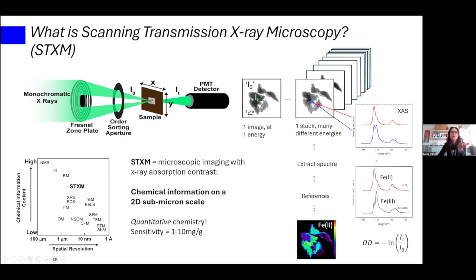So I've shown it to you here for the iron edge, but you can do other edges as well. We do cover the carbon edge, the nitrogen edge, the oxygen edge, the calcium edge, you name it, we cover quite a lot. And for all of these edges, you can get chemical information on a 2D submicron scale. So this image would be typically something like 5 by 5 micron, maybe. And the pixel sizes that you would use, you would match to the kind of resolution scale that you need. So maybe 30 nanometers or 100 nanometers, depending on what you're looking for. Moreover, as I said, these colors come with actual numbers. It's quantitative chemistry. And the sensitivity of the STXM method is roughly between 1 and 10 milligram per gram for the different edges. So it differs a little bit which edge you look at.